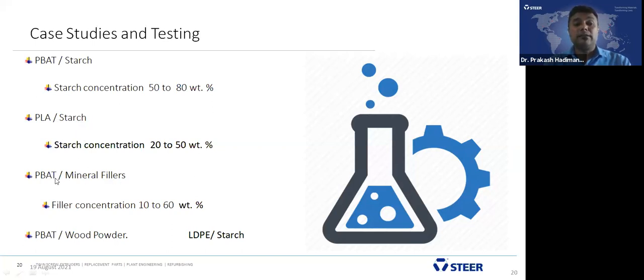And the third category, PBAT with a mineral filler. In the mineral filler, we went up to 60 weight%. One is we have used calcium carbonate mineral and also talc mineral. These two we have utilized with PBAT. And PBAT with wood powder and also lignin, we use up to 40% filling of wood powder and the lignin.